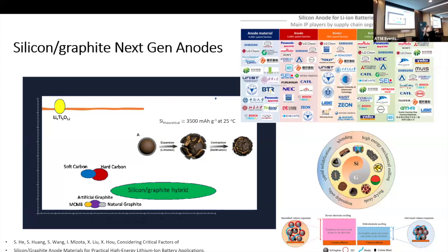But the big problem with this is the exfoliation and pulverization of the material. As you put lithium in, take it out, put it in, take it out, it breaks up the silicon into tiny pieces. So there's a lot of new research going into different ways of mechanical milling, and using vapor deposition of carbon coatings on this material to try and improve the performance.